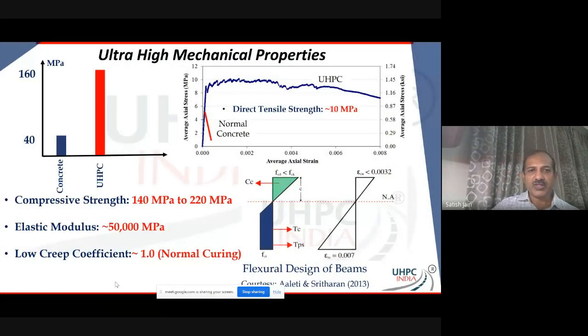Yeah. So to give you some ideas, on the left side, I'm showing comparative compressive strengths in the range of 140 to 220 MPa. And why do I limit to 220 MPa? That's in general what you're going to get. You definitely can go to 250 also. And there are certain ways and means that you can achieve 350 MPa, 400 MPa. So there are ways to do that, but that is outside the realm of normal use of UHPC in construction. So that's about the compressive strength.